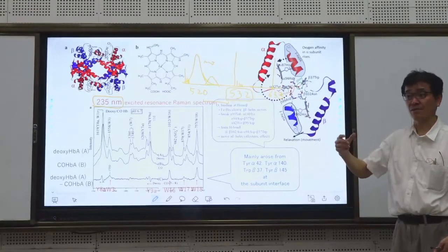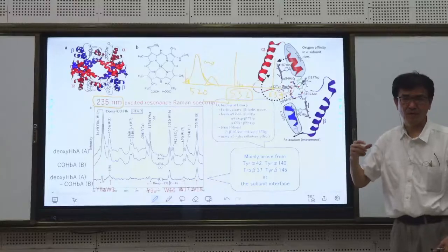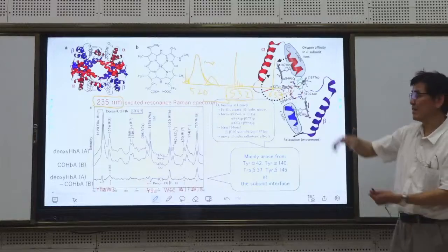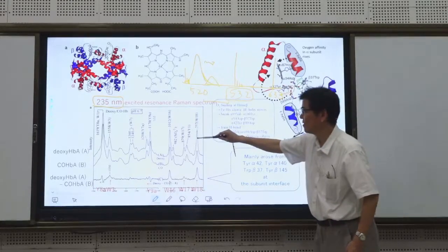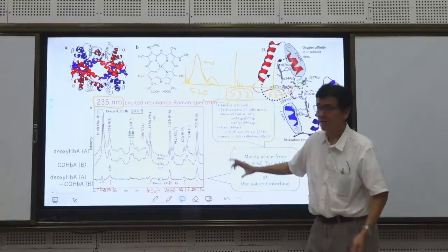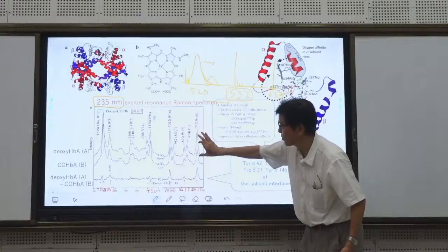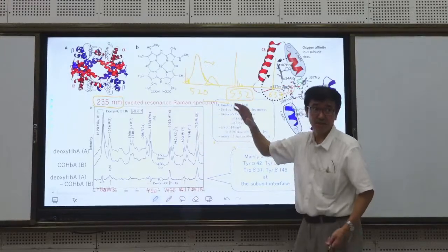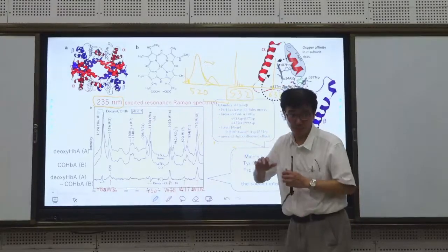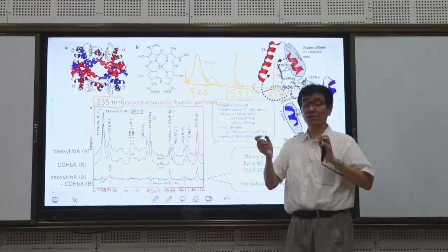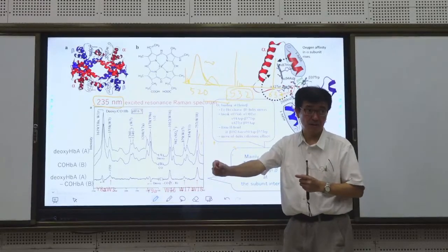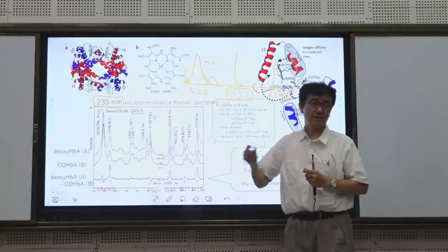Then I start the UV resonance Raman measurement with 1 or 2 milliwatt, and after 5 minutes, the intensity becomes 70%. So the intensity becomes smaller and smaller over time. That is, UV irradiation damages the sample, so decomposition occurs. So every 5 minutes, I replace the sample with a new one.